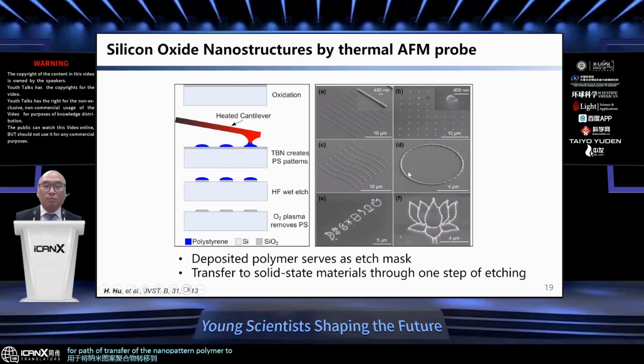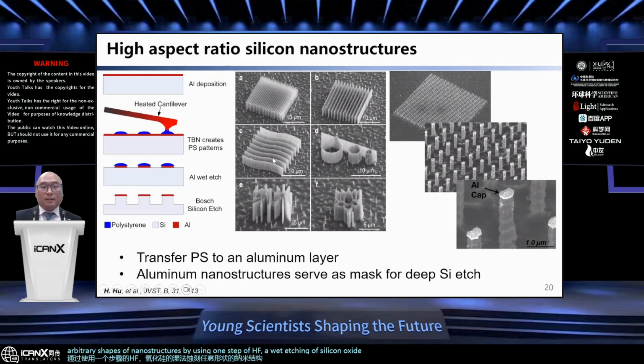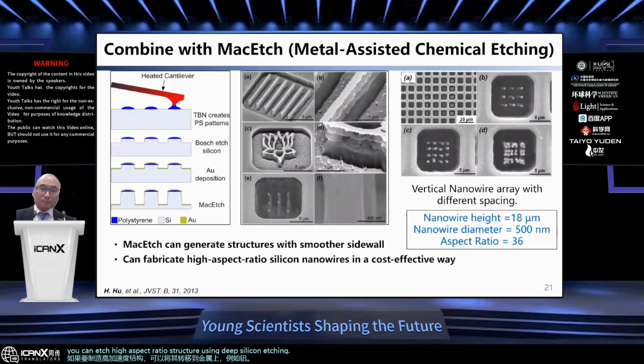So you can see we can make silicon oxide arbitrary shapes of nanostructures by using one step of HF wet etching of silicon oxide. If you want to make high aspect ratio structures, you can transfer that to metal, for example, as aluminum. You can etch high aspect ratio structure using deep silicon etch process.